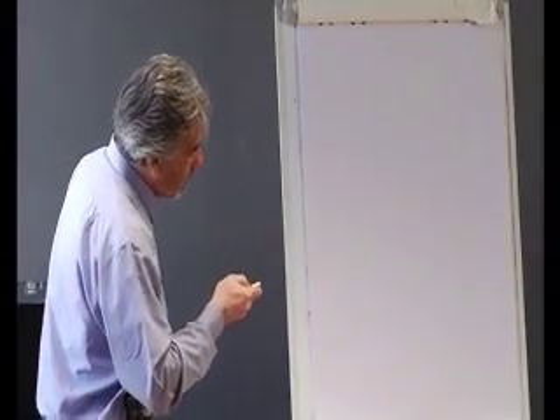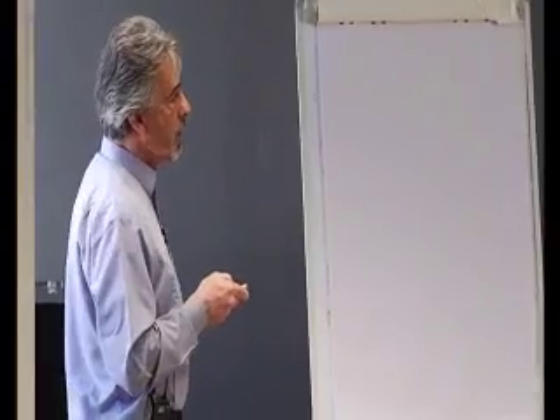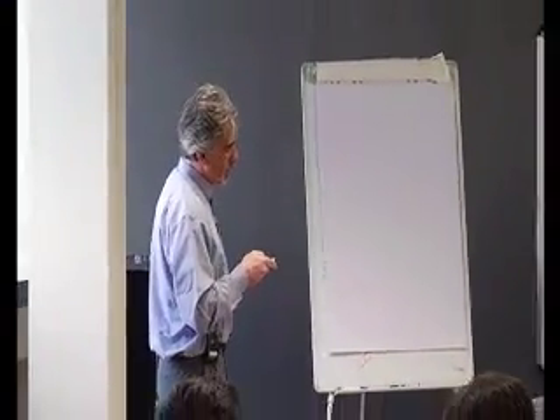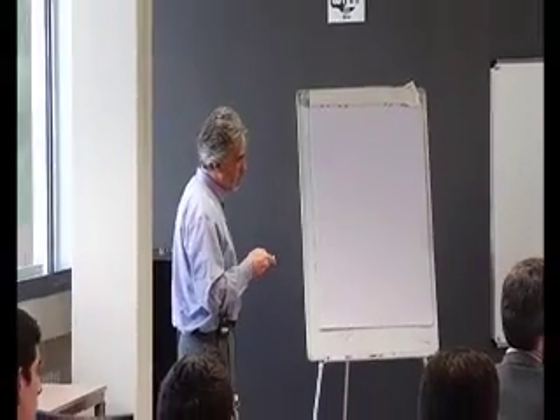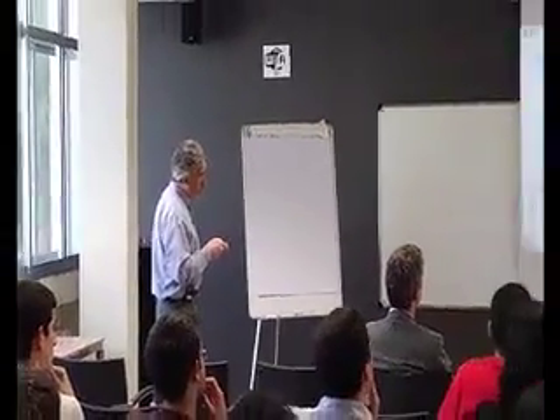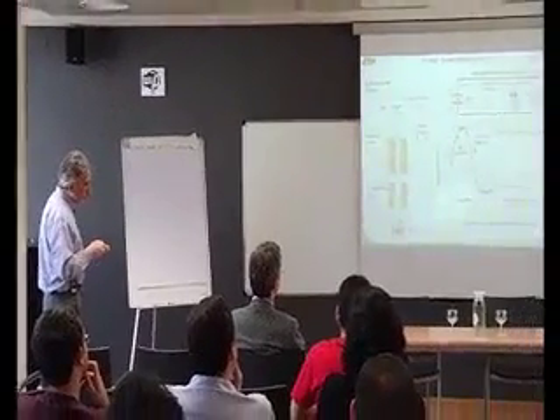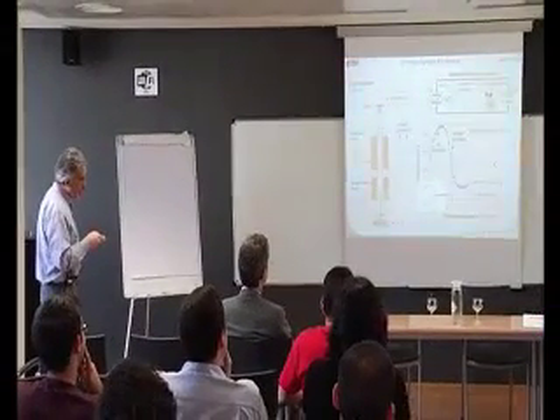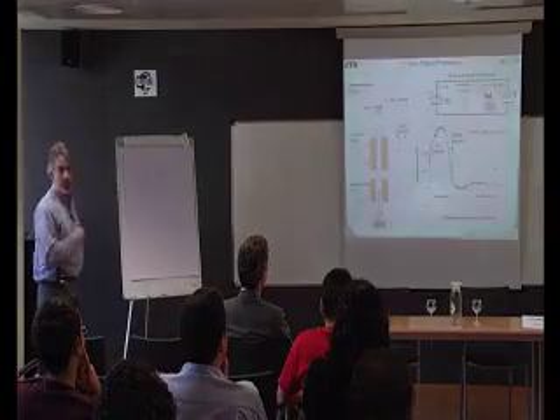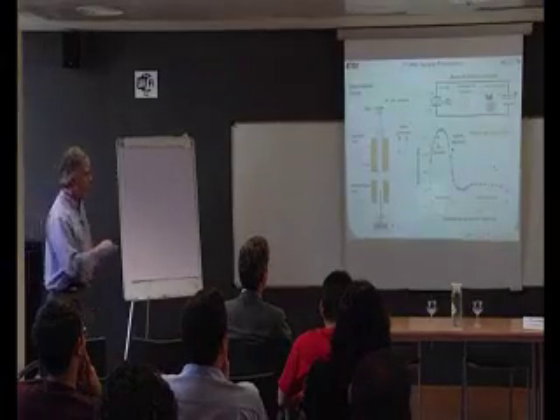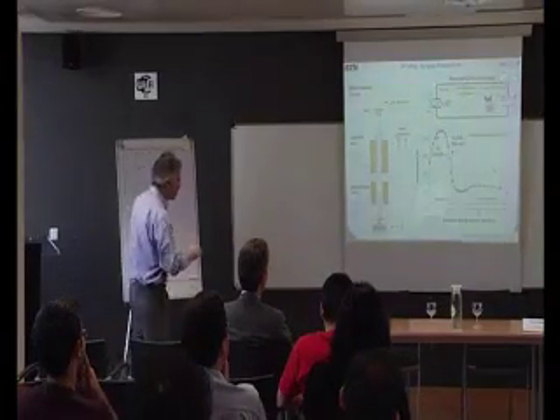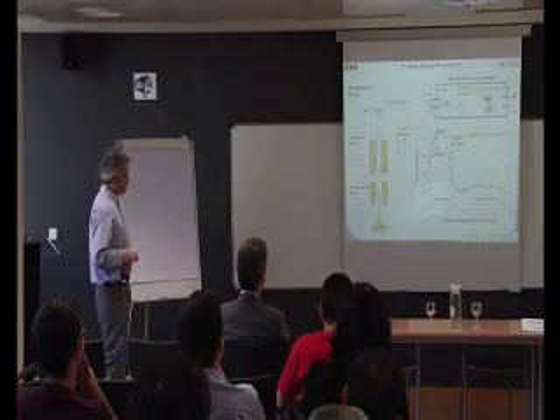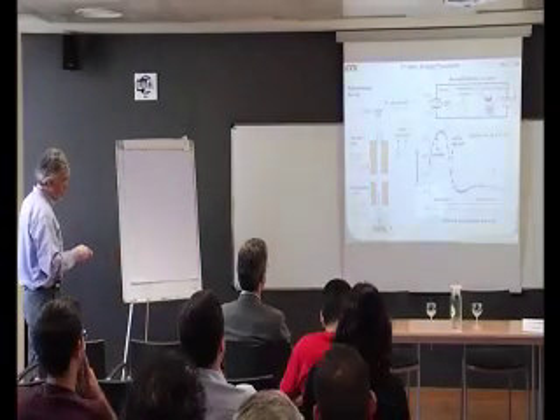Here on top of the slide you see what we call the aerosol reactor concept, in which we mix, in this case I'm writing steam, but it can also be CO2, and zinc vapor, rapidly quench to form the nanoparticles that react in situ to generate hydrogen and the zinc oxide particles. And we have realized this concept in a vertical tube with 2 furnaces.